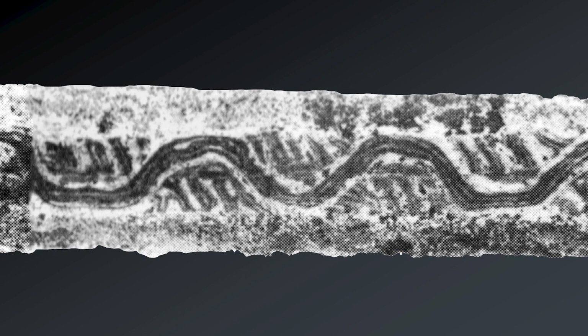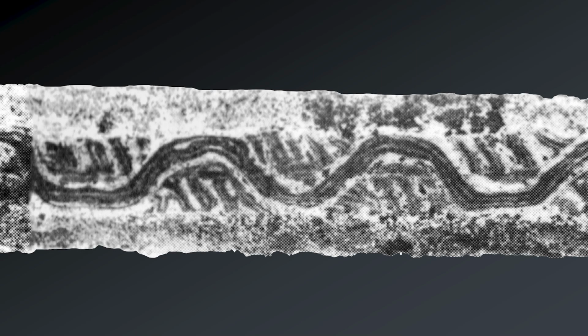So not to get you all confused, let me describe now what I think this pattern is as I understand it today. So take the information I present to you with a grain of salt. What I see now is that the smith used the same billet arrangement as he did for the chevron pattern. This one. The serpent itself is not a clever manipulation of the billet created by grinding, which is what I thought at first. The serpent is an actual inlay. A single rod was drawn out to length, then shaped into the serpent and inlaid into the core of the blade, which itself has a 3-bar billet as its main pattern.